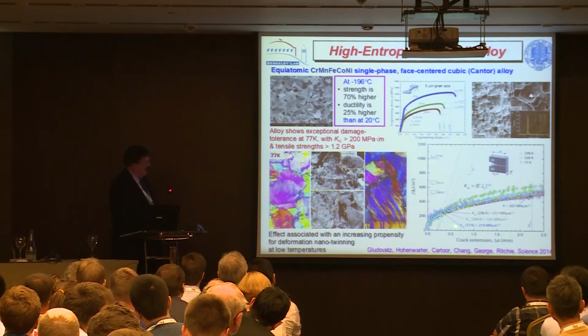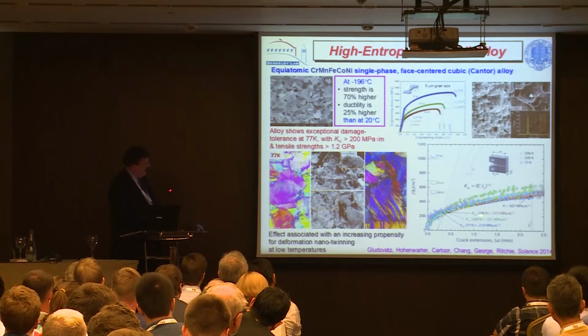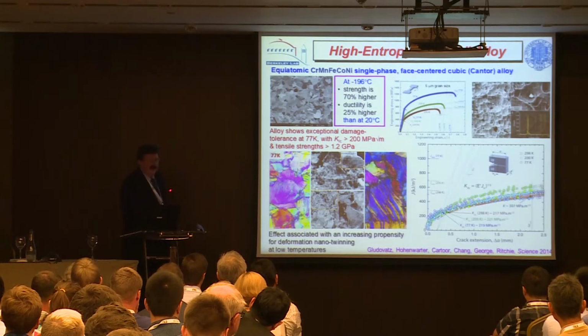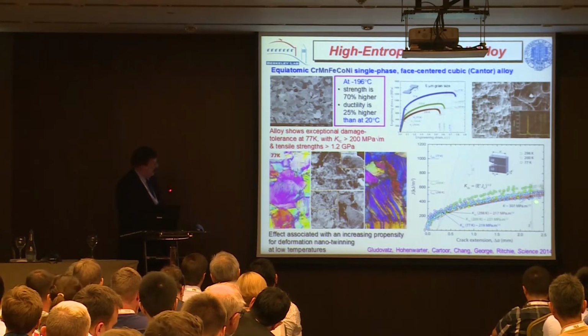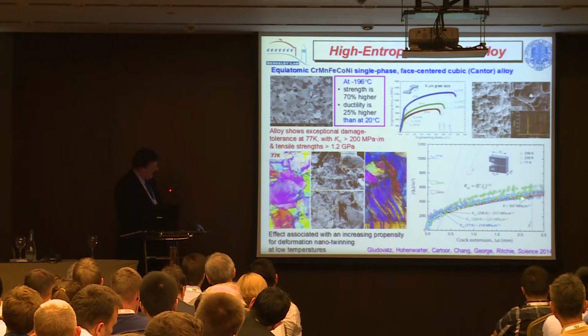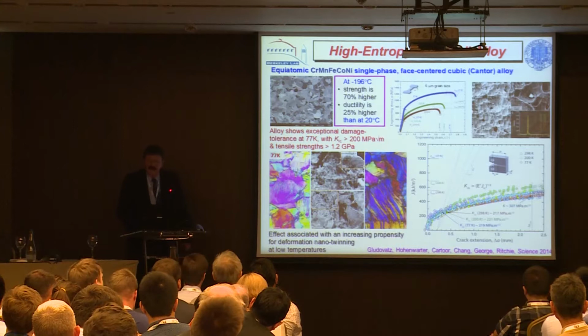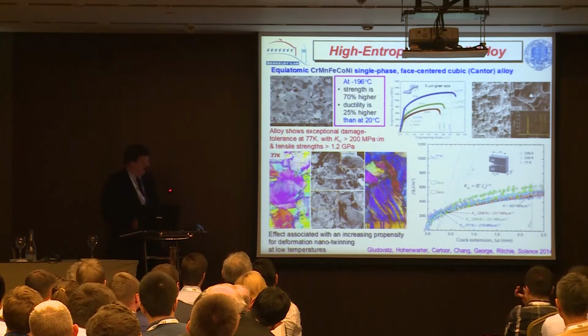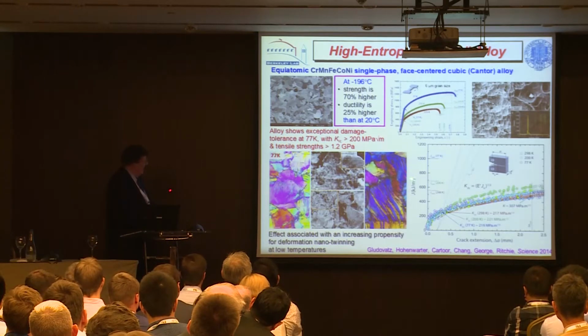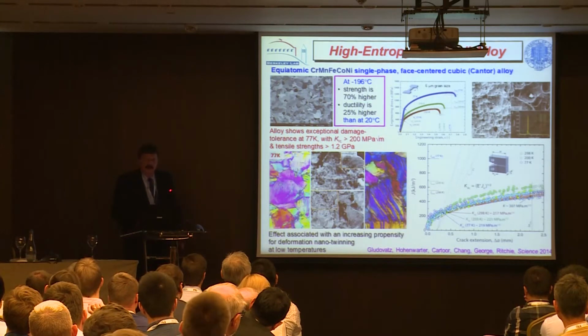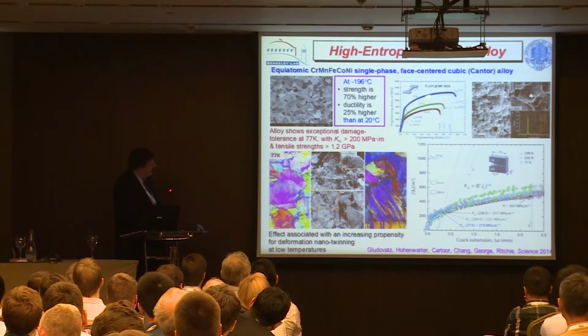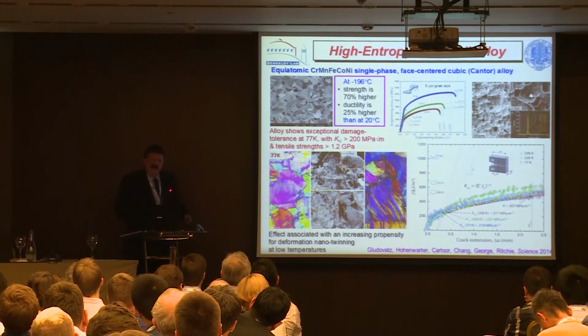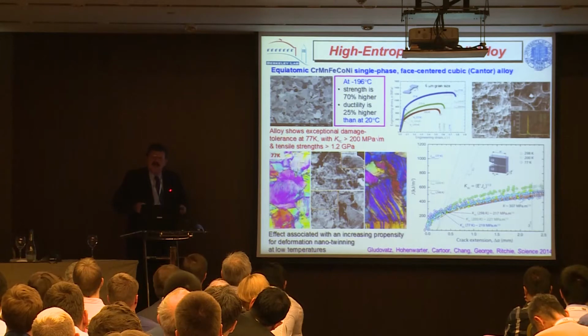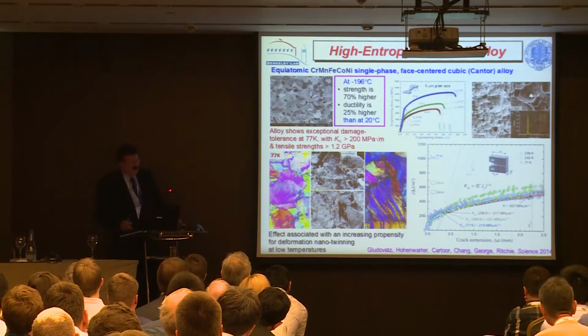These are JR curves. These are all valid toughnesses, and we got these amazing toughnesses of more than 200 megapascal root meters at crack initiation, at room to liquid nitrogen temperatures. And the crack growth toughness, which is perfectly valid in this size of sample, was up around 350 megapascal root meters. And these are enormous numbers. You look at the structure, and at liquid nitrogen temperatures, you see a lot of twinning, nano-twinning. And this is really the key here, this steady strain hardening in these materials. The hardening, of course, is good for hardness, but the strain hardening suppresses necking, so we get good ductility too.